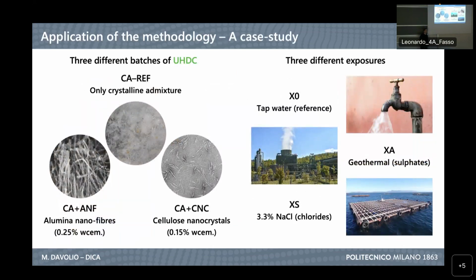And this methodology was not only proposed, but also developed on a case study where we addressed 3 different batches of UHPC, where the reference one had only the crystalline admixture in addition to the mix design I already described for the autogenous healing. While the other 2 batches, having also the crystalline admixture, also had, in one case, alumina nanofibers, and in the other case, cellulose nanocrystals. And we will later find out the contribution of these nanocomponents to the performance of the material. On the other side, we investigated 3 different exposures.